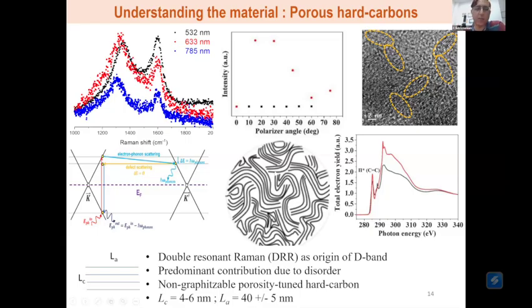What this cartoon shows you is that at short range, they behave as graphite. That is, they are well-ordered graphene layers sitting one on top of each other, interacting through van der Waals interactions. But when you go to the long range, this order collapses. So it's neither a completely amorphous material nor a completely crystalline material. It's a mixture of short-range ordered domains, which give it a certain amount of crystallinity, and which then break down over the long range, which gives it a certain amount of amorphousness.